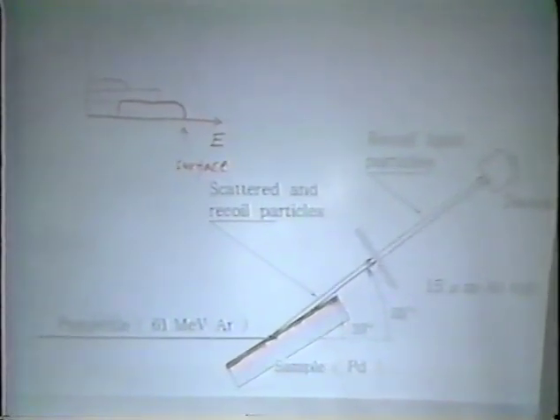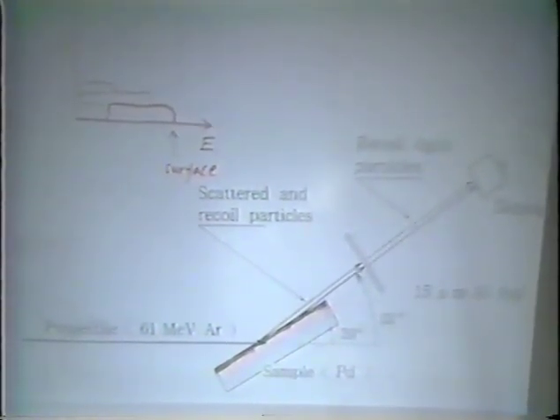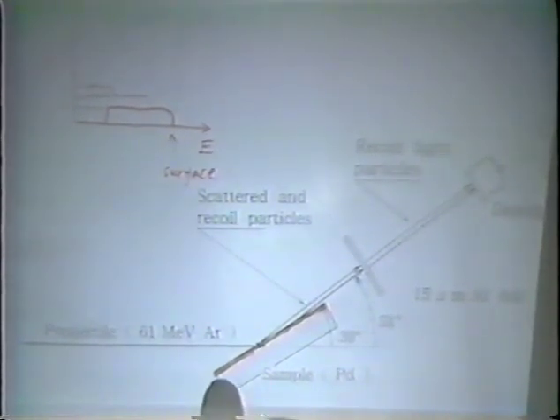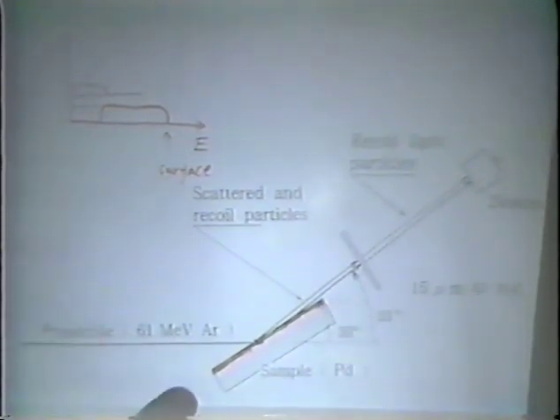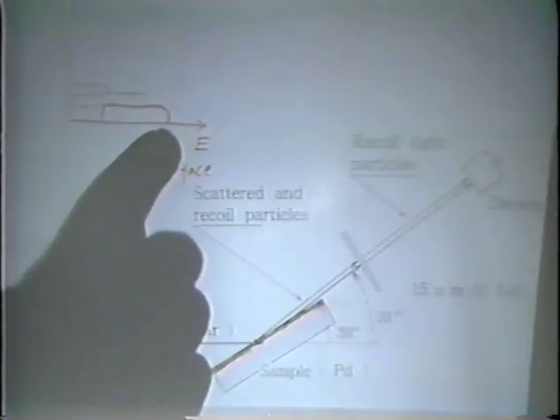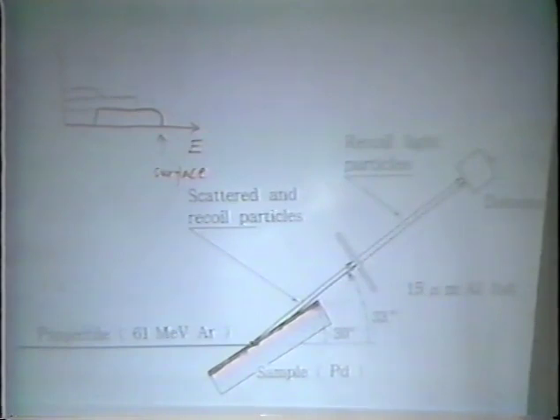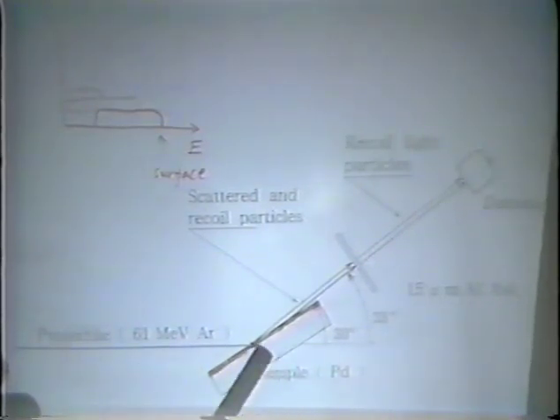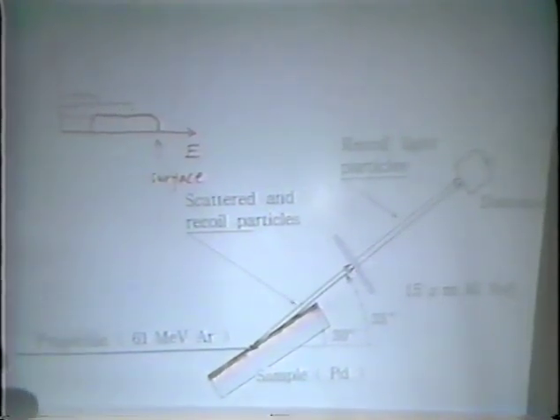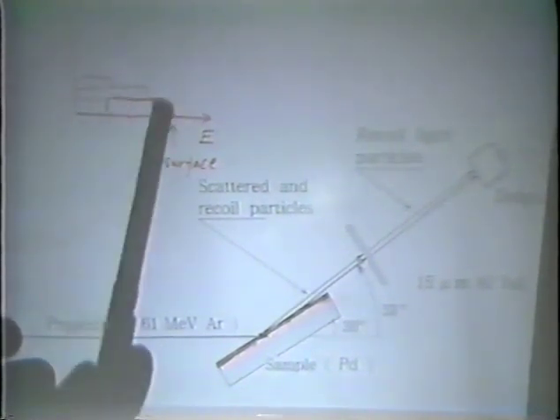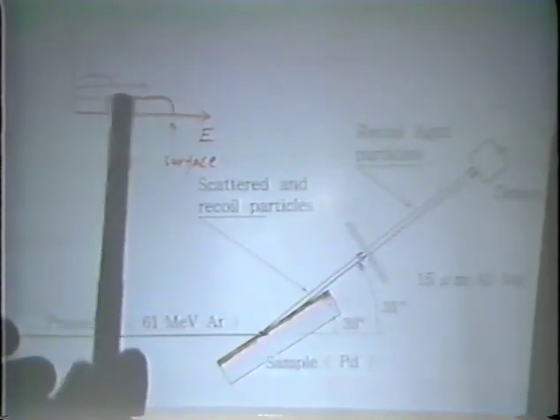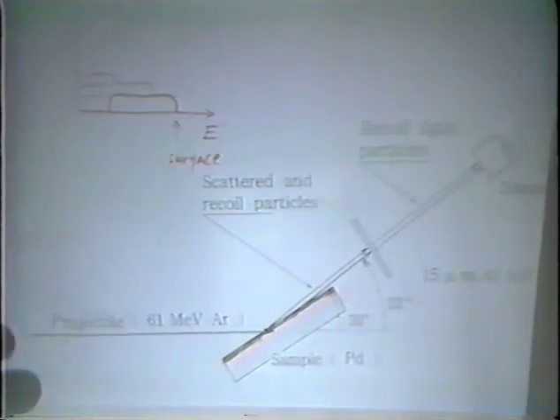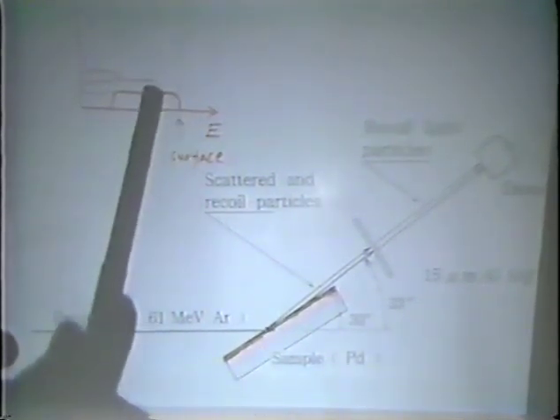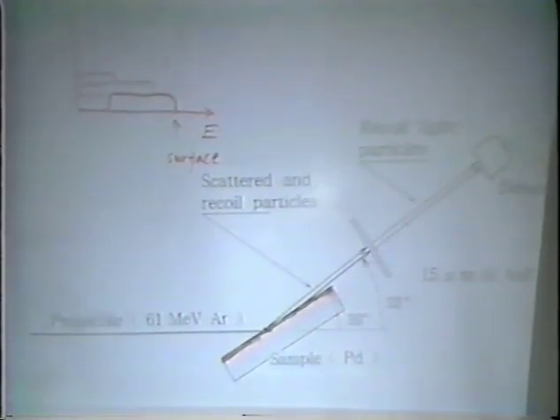This is a very nice technique using Coulomb scattering with heavy ions. You can see that if you have some content in the sample, you see the Coulomb scattering. If Coulomb scattering happens on the surface, you see a certain energy in the scattered particle. Then, depending on the depth, how much is in there, you have this width of the spectra. So you can see how much content is involved by this height and also how deep it is in. And if you have other elements or other particles, because their mass is different, they start from different energies. So you can separate other particles.